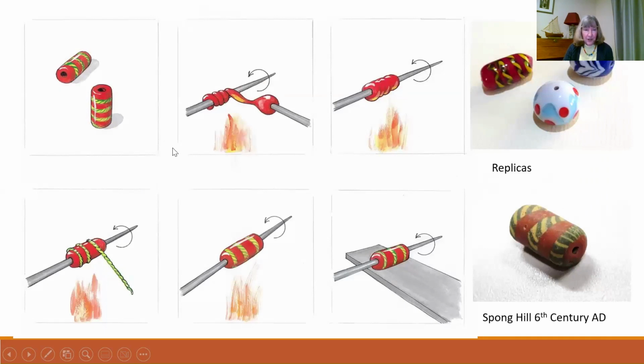So here's how these particular British beads were made. Here's one, and here is an original. This is a replica up here, and down here is a 6th century bead. My replicas, I feel, are beginning to look very, very like the original ones. So you make a cylinder bead, then you lay the end of your twisty on the beginning at the top of the bead, and quickly rotate, and the twisted stringer winds itself round. And finally, here we do have some marvering to smooth the bead. It will sink in, but in order to keep the ends neat, you might roll again to get a nice round shape. And you can see here the shape of it.